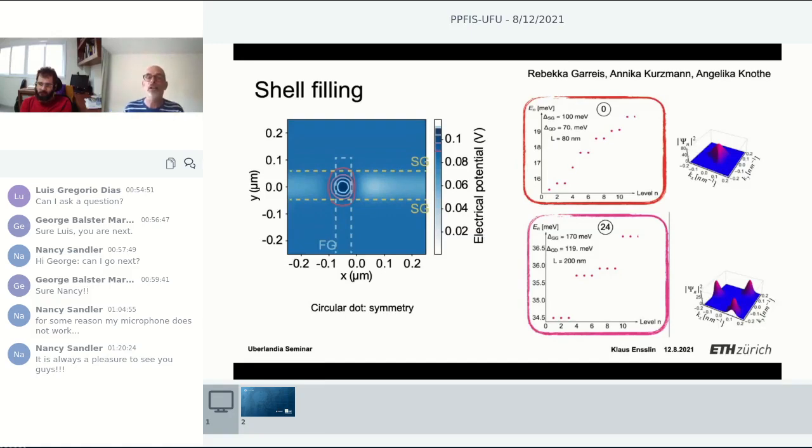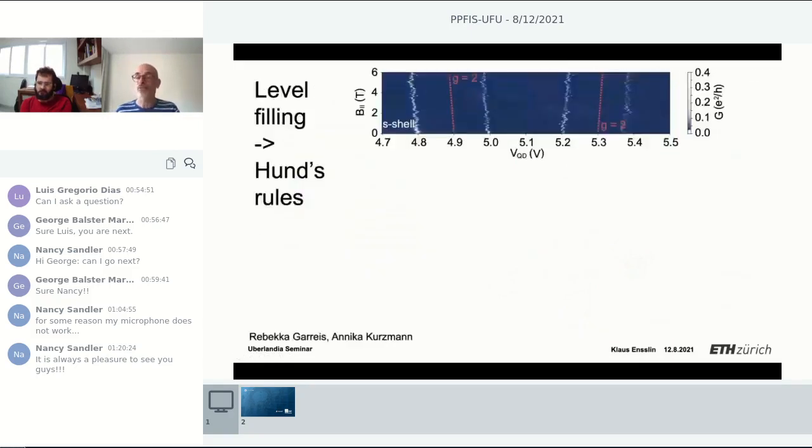So you see, for a large quantum dot, all of these states occur in triples. And the reason is the trigonal warping in this state. So now if we go back to our experimental data, we understand the 12 electrons. That's a threefold degeneracy from trigonal warping, plus two for spin, plus two for valley, and we are there.